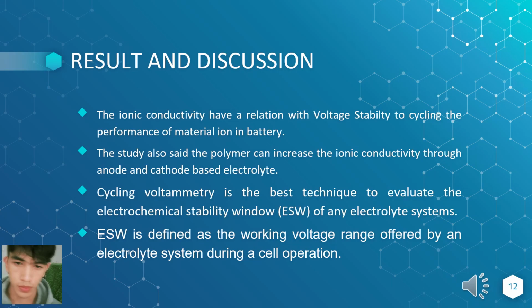From the research, the ionic conductivity has a relation with voltage stability and cycling performance of the material in the battery. The study also said the polymer can increase the ionic conductivity through anode and cathode based electrolyte. Cyclic voltammetry is the best technique to evaluate the electrochemical stability window (ESW) of any electrolyte system. ESW is defined as the working voltage range offered by the electrolyte system during cell operation.